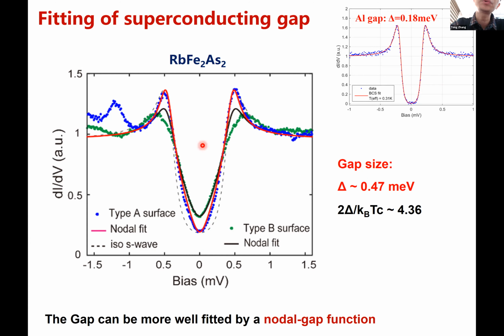And here I also want to say the V-shape is not due to our resolution not being high enough. That's because on the aluminum film, the gap is even smaller, but it is a fully gapped iso-s-wave, and we can still resolve it. The gap bottom here is still U-shaped.